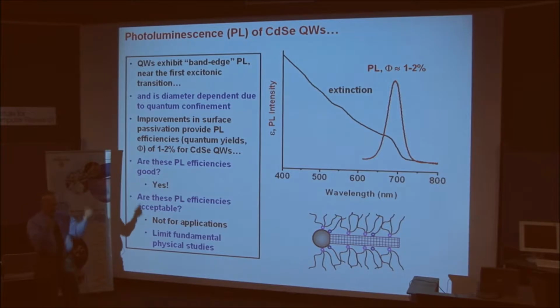If every photo-generated electron-hole pair recombined and re-emitted the photon, our efficiency would be 1 or 100%. The fact that this is only 1 to 2% says when we generate 100 excitons, only 1 to 2% of them are recombining radiatively. So is that good or is that not good? Well, we'll be discussing that at some length. It turns out that those sorts of photoluminescence efficiencies are actually very good in comparison to what's currently in the literature. But obviously, for applications or to enable fundamental physical studies, that's pretty low.